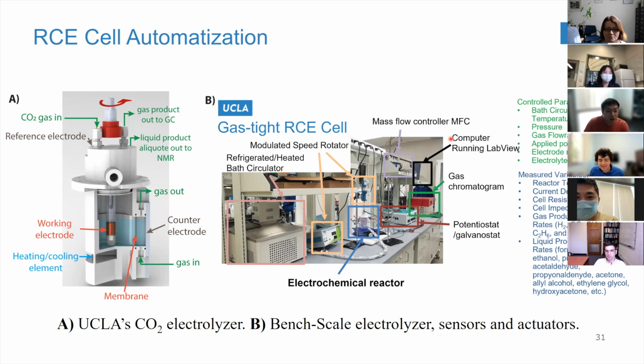So would the shape of the rotating electrode make any difference? So no. What is unique, and obviously we did not know it when we started working with the cylinder, is that the cylinder electrode is unique in the sense of mass transport. As you rotate the electrode, the mass transport is actually happening in and out of the surface at each point. If you have looked at the description of mass transport in a rotating disk electrode, you have the flux going towards the surface of the disk, and then the molecules move outwards. And so that limits it, so essentially your concentration of species is changing as you move towards the outside of the disk. That's why commercially you find disks that are always very small, 5 millimeters or so. You cannot go larger because then those effects become much more significant.